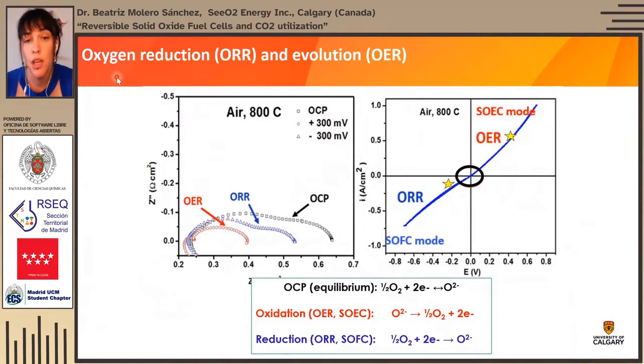Now, here I'm just showing a quick example of how we would do something like that. Here I'm showing the oxygen reduction and oxygen evolution reactions. Those are the two reactions that occur at the oxygen electrode in the SOFC and the SOEC mode. When you perform electrochemical impedance spectroscopy at what we call the open circuit potential, or the black curve, you are measuring the reactions at equilibrium here in the middle. This is a CV, or cyclic voltammetry, a different technique, but they're related.